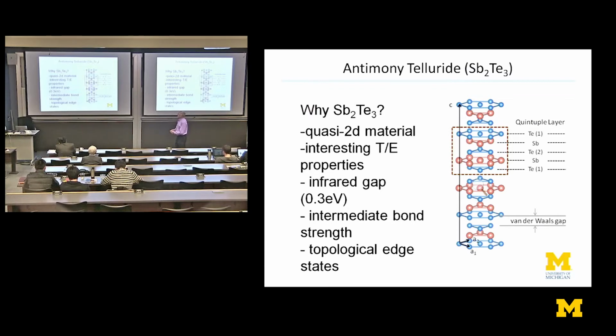with moderate energy density. It also has a van der Waals gap. Every 5 layers here, there's a van der Waals gap. In other words, a weakly bonded package of layers, weakly bonded to another quintuple layer. And as you go down the c-axis here, you have a series of layers. So this is a prototypical layered compound or quasi-2D material.